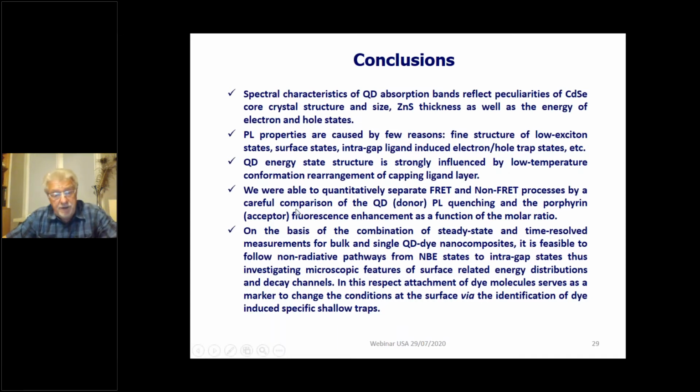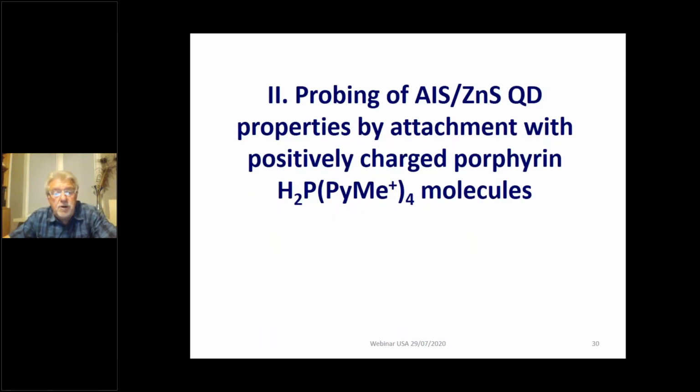In fact, we have succeeded in separating energy transfer from other non-FRET processes. These results should be taken into account when we prepare such systems for possible application in biomedical investigations, especially when we prepare, for instance, new agents for photodynamic therapy of cancer.